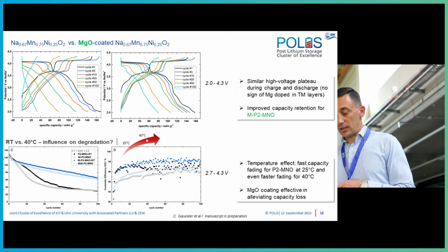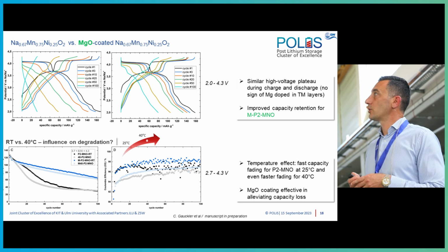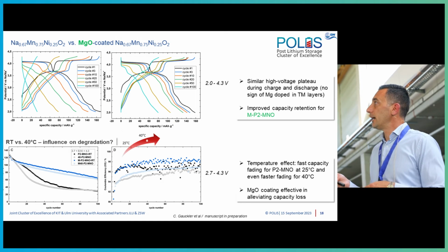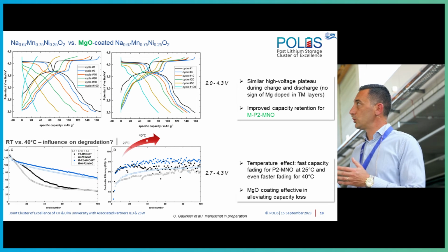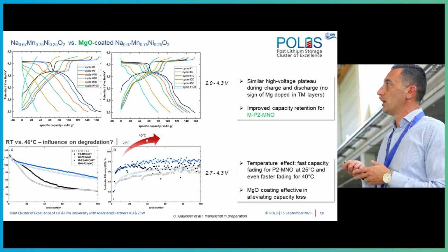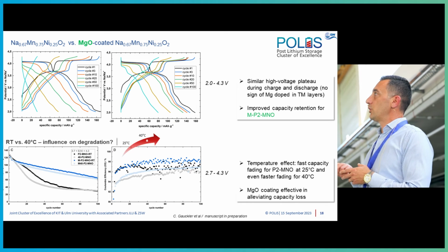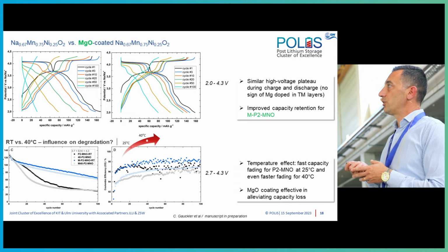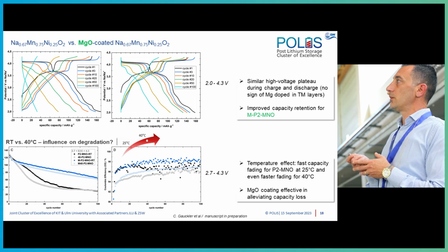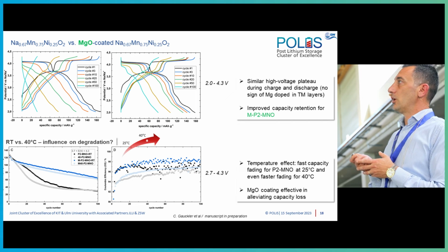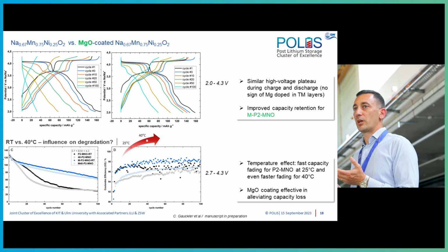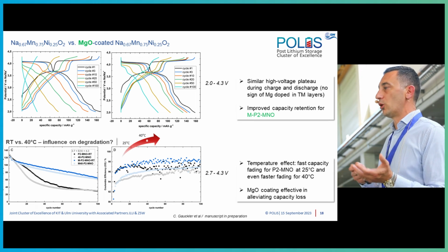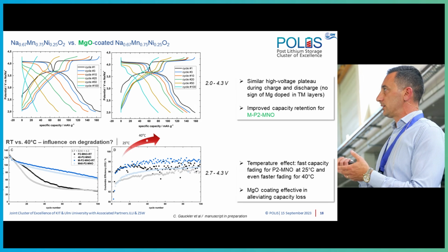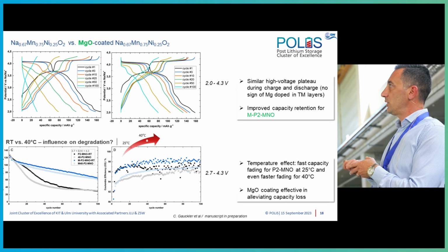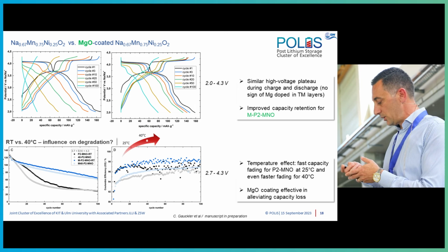Now, going to the magnesium oxide-coated material. In the upper side, we see the two graphs, again a comparison of the uncoated and magnesium oxide-coated material. You see that basically the high-voltage plateau is not affected, so it's a very similar shape of the galvanostatic profile, and this is in agreement with the fact that we don't have magnesium doping in the bulk. Still, we have a better capacity retention in this potential window.